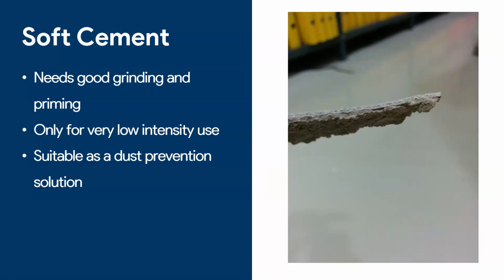Now, why did it fail? Well, there are several reasons. Soft cement is uneven, so you need to grind it and prime it really, really well. I only recommend these applications if you are going to use it for low intensity use. So if it's going to be like a storage space where hardly anyone ever walks in there, go ahead and apply epoxy. If you just don't want any dust in the room, it works. However, if you're planning on heavier wear and tear, if you're going to be walking on the surface every day with pallet trucks and shifting things around or parking cars, it's a matter of time before the cement underneath starts to crack and the epoxy will crack with it.